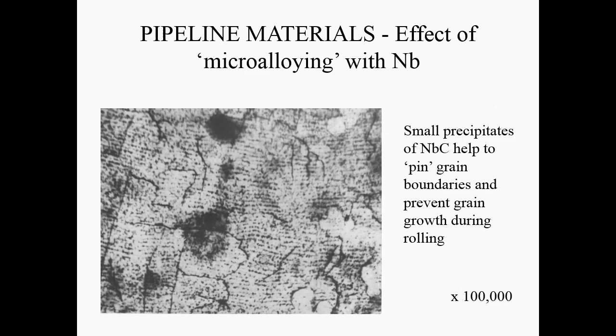So here's a microalloyed steel. These are grains of ferrite, which is the low temperature form of iron, and you can see it's polycrystalline. There's another grain here, there's another grain here that's quite big. And the spots on the surface are the precipitates of niobium carbide that are used in this particular case.